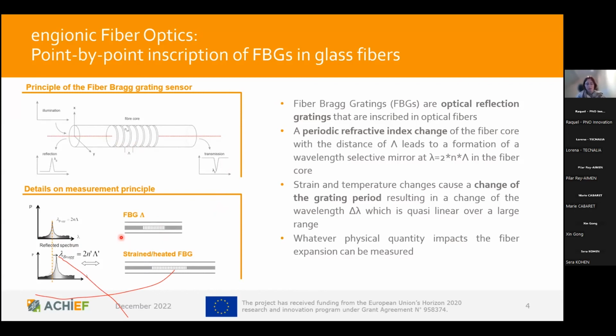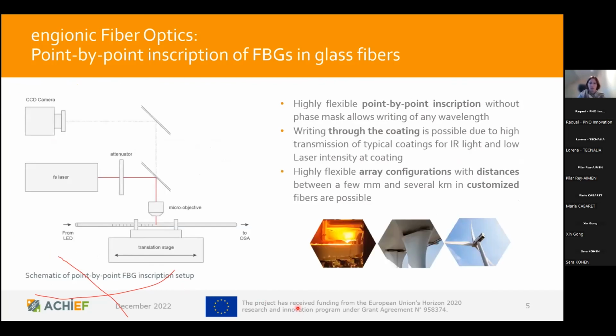We can easily reach resolutions with the sensor of 0.1 degrees Celsius for temperature, or a microstrain can also be measured with these types of sensors. So at engionic Fiber Optics, we achieve these periodic refractive index modulations with the point-by-point inscription method. So we use a femtosecond laser source and basically shoot defects in a point-by-point manner into these optical fibers.